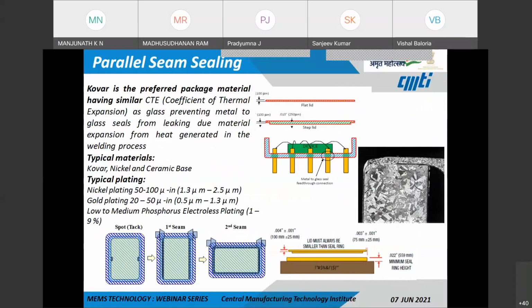In parallel seam sealing, the most common lid material used is Kovar, because it has a coefficient of thermal expansion close to glass, and which also prevents the glass seal from leaking due to the material expansion from heat generated in the welding process. So typical materials are Kovar, nickel, and ceramic bases.